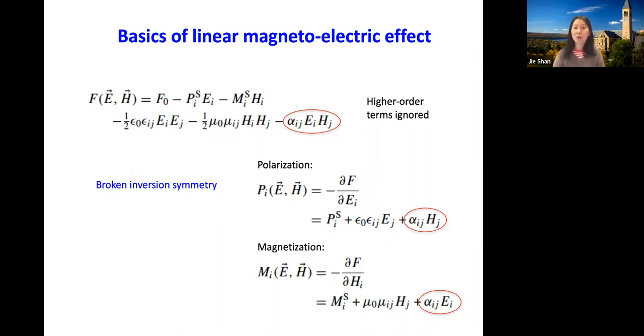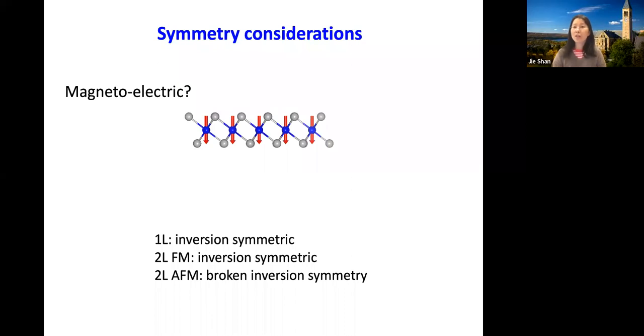And by a very similar argument, for this to be non-zero, we also need to break time reversal symmetry because, under the time reversal operation, magnetization changes sign, but electric field doesn't. So just from this basic symmetry analysis, we know if you want to get a non-zero linear magneto-electric effect, the material has to have broken both inversion and time reversal symmetry. So we are dealing with those ferromagnetic or antiferromagnetic materials, so we don't need to worry about time reversal symmetry. It's broken. How about inversion symmetry?